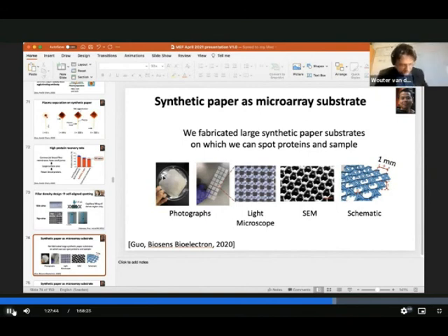So what you do is you have a mask on the top and you have holes. Every top of a pillar was a hole in the mask. And the size of the hole, whether circular or square, and the pitch will determine it. So if I make a hole of 20 micrometer, I have a pillar of 20 micrometer. If I make a hole of 100 micrometer, I have a pillar of 100 micrometer. So I can control that. And the depth you control by the thickness of the layer. If I have a very thin layer, I will only have one row. But if I have a very thick one, I can have many, many rows on top of each other. So I can make thick paper by controlling the thickness of the film to start with.